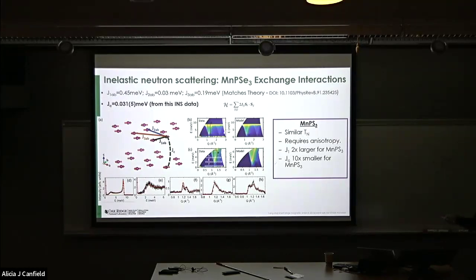You can't start to model the data. You have to put in a J_c interaction, which is an order of magnitude larger than the J_c interaction for the sulfur version. It starts to become comparable actually to some of the in-plane interactions. So again, this is really showing that the Se3 is behaving like a bulk three-dimensional material, even though you can exfoliate it down to a single layer, whereas S3 is much closer to the two-dimensional limit.